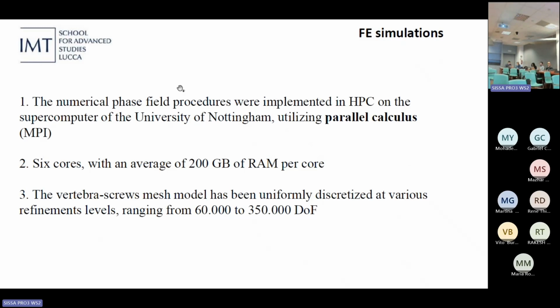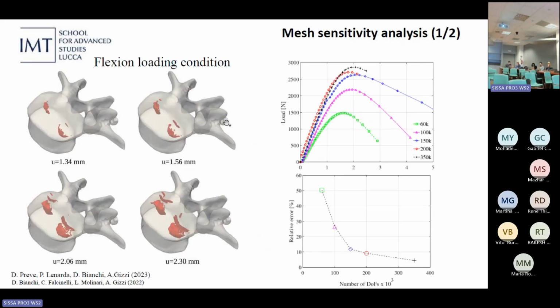Regarding the high-performance computing, the simulations were run on a supercomputer at Nottingham University using MPI, splitting the problem across 6 cores. We considered meshes in which the number of degrees of freedom ranges between 60,000 and 350,000. This is a mesh sensitivity analysis in which we considered a flexion loading condition. So the screws are pulled by the heads in this way, and we can see the formation of this kind of spherical region of damage around the end of the screws inside the cortical part of the body, the inner part of the bone.